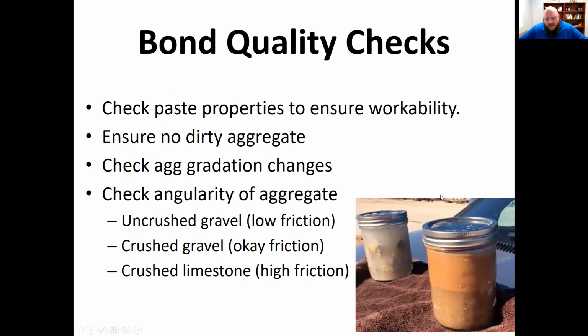One time somebody called me up and said, Dr. Cook, I'm having real bad strength issues. I'm having reductions of 30 to 50%. Can you help me out? What I found out really quickly was that the aggregate sources actually changed. You can see here, this is called the mason jar test over on the right. The coarse aggregate's pretty dirty. This is after an hour of setting.